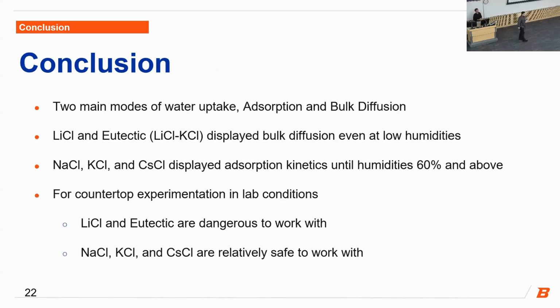So in conclusion, we found that there were 2 water uptake methods for salts. There's adsorption and bulk diffusion. We found that lithium chloride and eutectic underwent bulk diffusion at relatively low humidities, while cesium, potassium, and sodium chloride would undergo adsorption up to relatively high humidities. And for countertop experimentation, though this is an overgeneralization, we can consider working with lithium chloride and the eutectic as fairly dangerous, while potassium, cesium, and sodium chloride is relatively safe if you're fine with up to 0.2% weight percent gain for your salts.